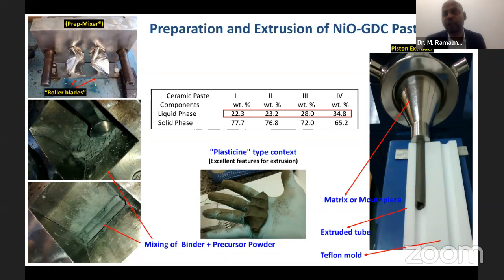Of course, there are 2 types of extrusion: automatic extrusion, and also manual extrusion. In the automatic extrusion, we have to have a big amount of paste, whereas in this case we need a very small amount of material, because we are developing mini tubes. We can sometimes say they are micro tubes, because the diameter and the thickness of the tubes may be in the range of microns, so the grains are at the nano level. This gives an advantage for fabricating tubes.